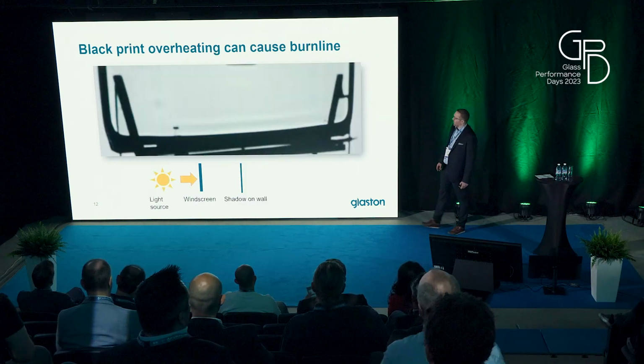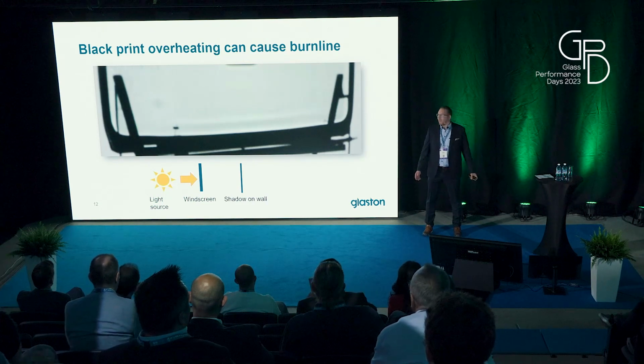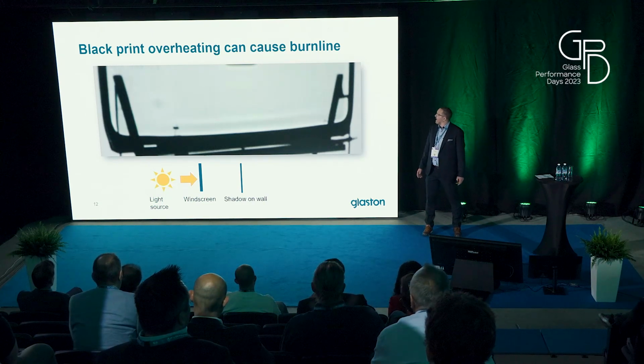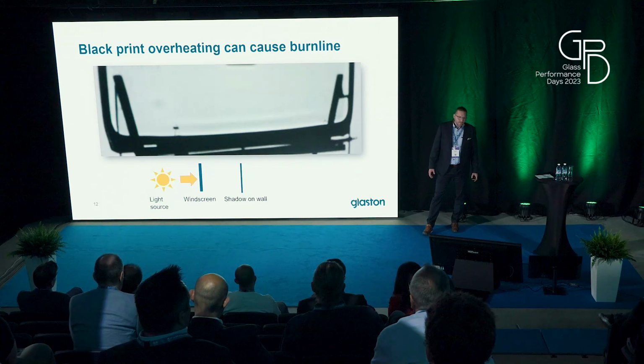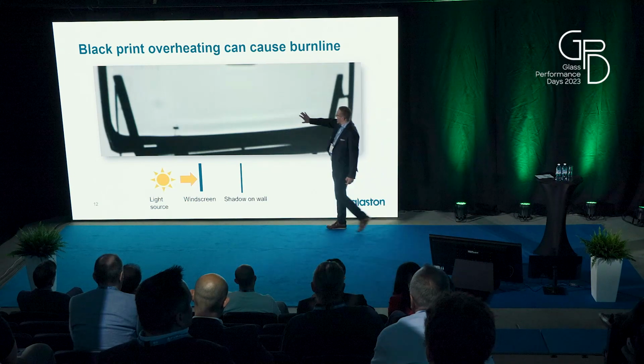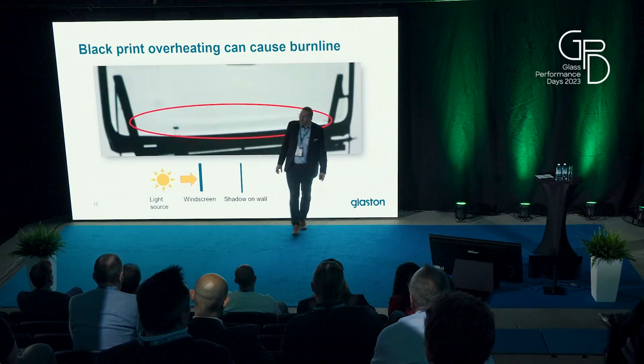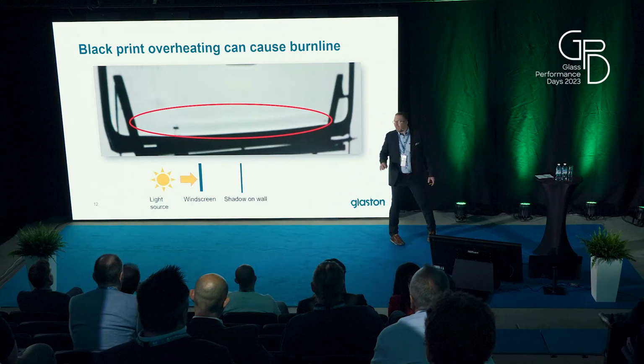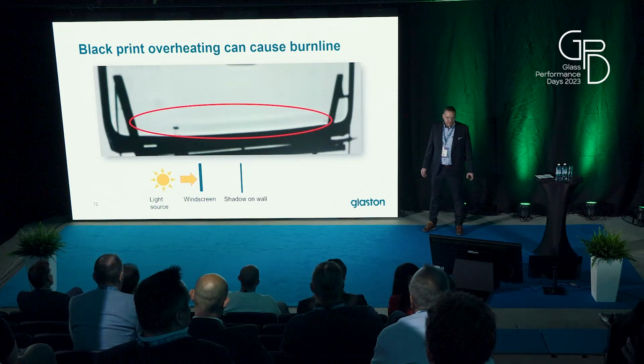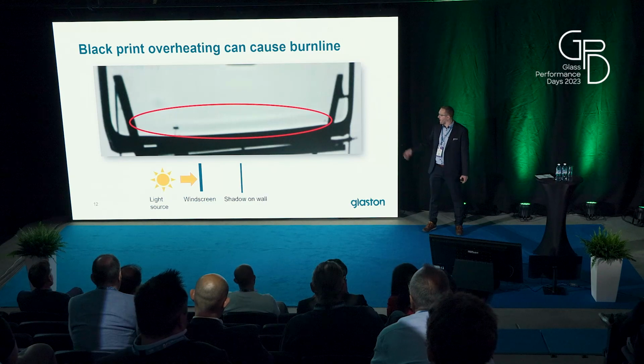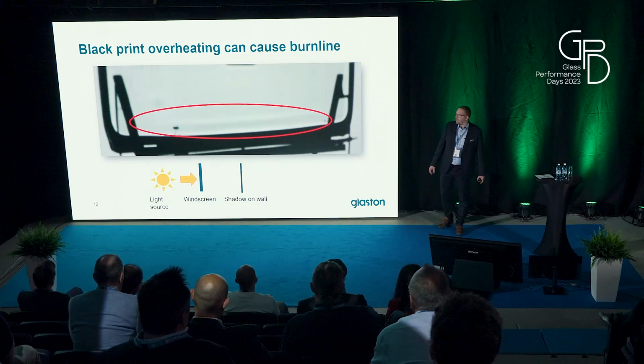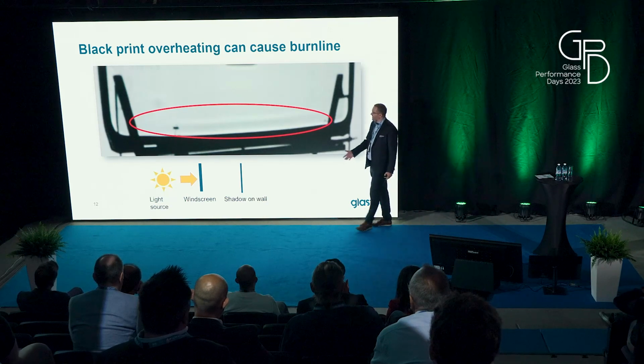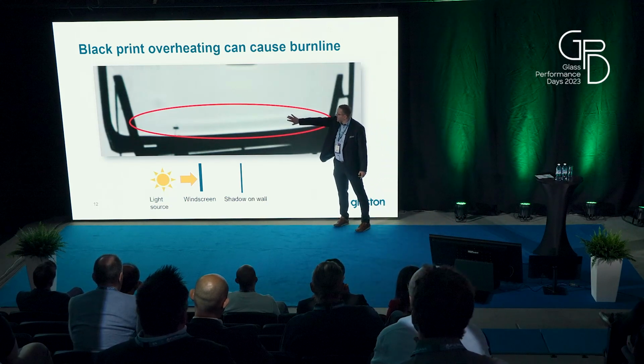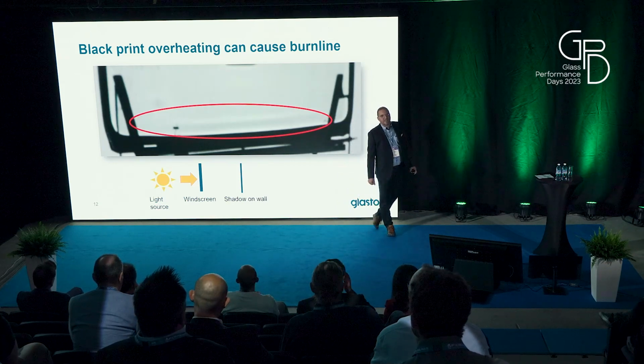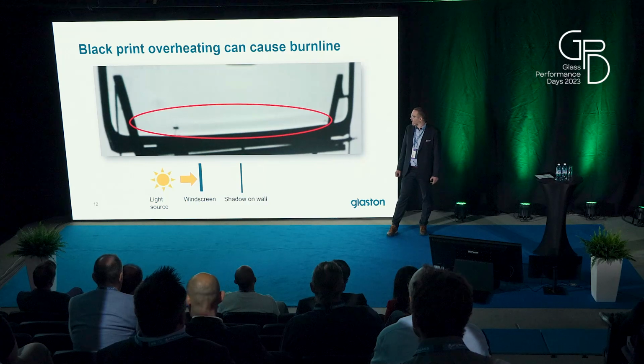And one thing we can help with is one visual effect called the burn line. You can see maybe whiter and darker areas. So this is a test case where we have a light source on one side, then a windscreen in the middle, and we are looking at the shadow of the windscreen coming from that. With that test, we can find if there are some problems, like in this case, this burn line, which causes defects in the visual quality and optics.